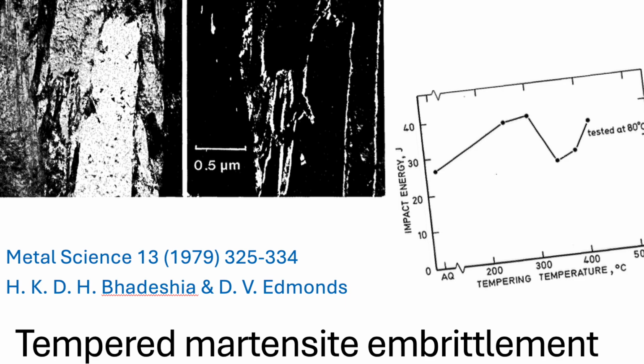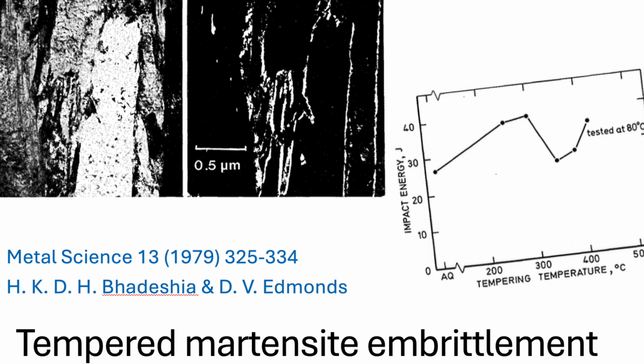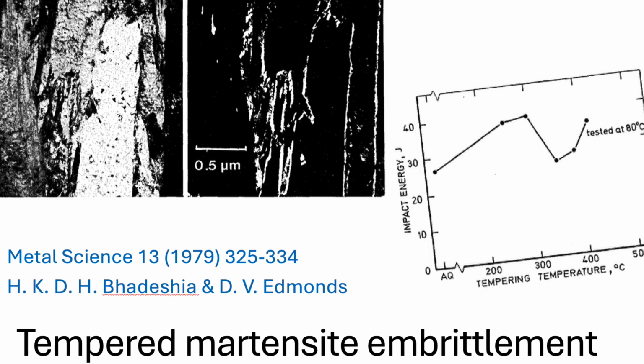Cementite. Okay, define that for us. Cementite is essentially iron carbide, Fe3C. It's a very hard but also very brittle phase found in steels. Right. And they found considerable amounts of this cementite precipitating out. But crucially, this cementite wasn't just random blobs. No, it adopted a specific crystallographic orientation relationship with the martensite matrix surrounding it. It formed a highly organized structural film right along the lath boundaries.